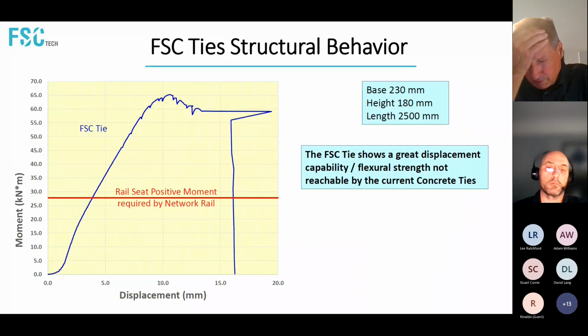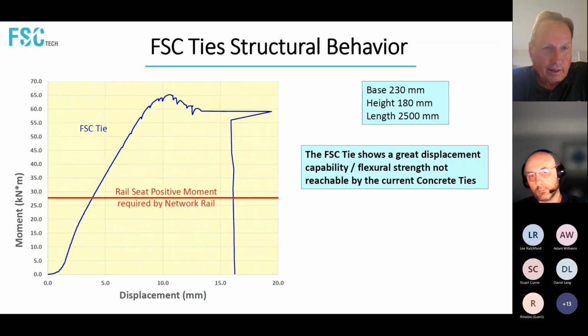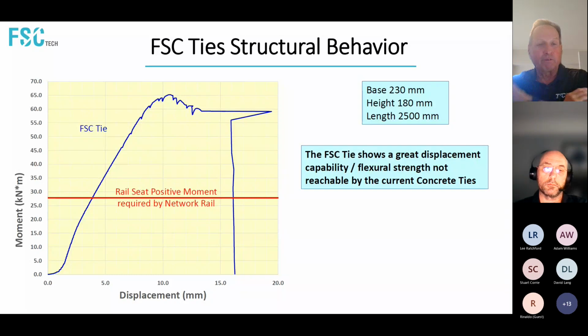So how does this perform in a structural test? Again, we talked at the beginning about the moment requirements that both Network Rail and AAR have for rail ties, and the primary focus is on the rail seat moments, which are higher, and then there's tests for the center section negative moment. But here's a test we did, and what we did is we made a very basic tie designed around the original wood dimensions, width of 230 and a height of 180, 8 foot long, and wrapped it and tested it.